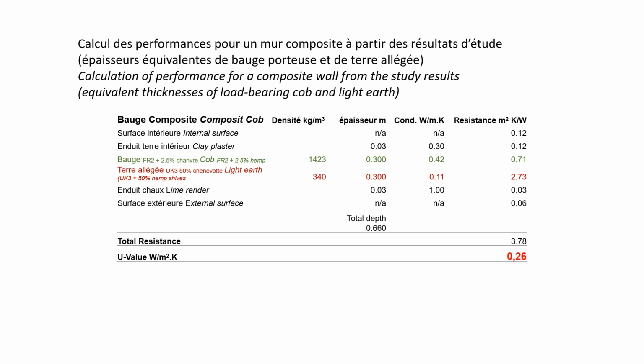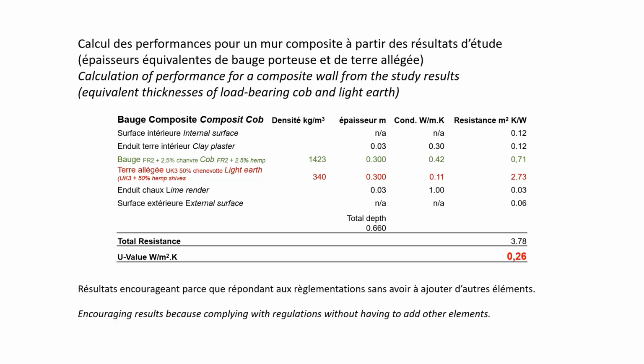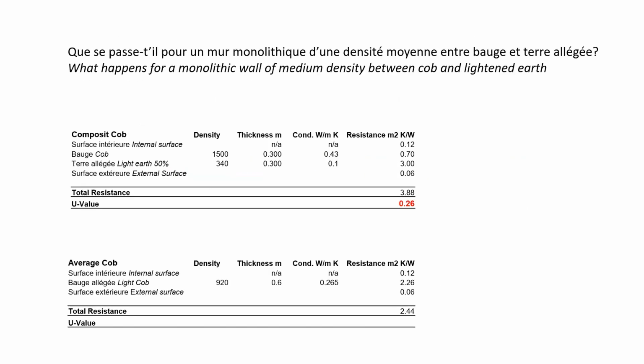And we got a U value of 0.26, which means, for our English friends, that they comply with thermal regulations per element, because there's a limit for walls of a U value of 0.3, so we remain below this limit using this combination of two mixes. So this means that you can comply with regulations. This was quite positive and significant for the future use of this combination of elements, even in France.